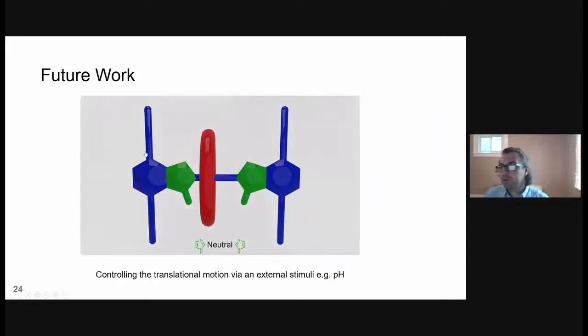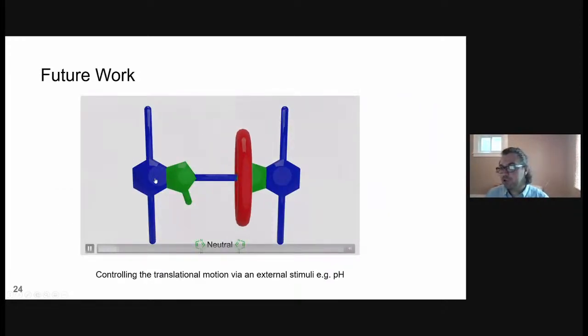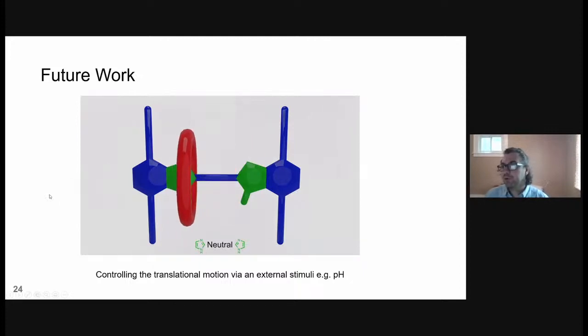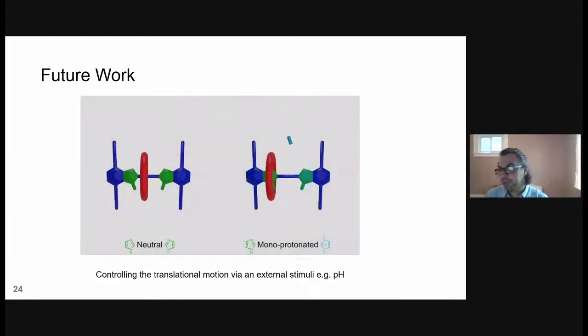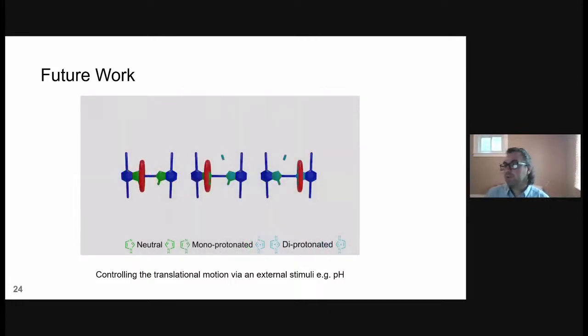And so in terms of where we're looking at moving this work in the future, as I alluded to a couple of times in the talk, one of the nice things about these benzimidazole-based recognition sites is their sensitivity to pH. And I mentioned that when we monoprotonate the linker, we can switch off the translational motion. We can also diprotonate the linker, and that switches back on the translational motion. It's just slower. And as we're now working with these nice and stable zirconium systems, we should be able to synthesize the MOF and then protonate it and be able to change up the dynamics with this external stimuli.